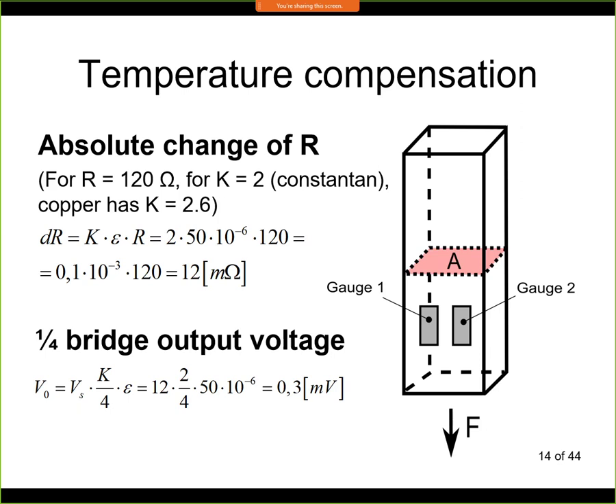What will be important will be the temperature coefficient of electrical resistance. So if I calculate the resistance change in ohms, here we have the gauge factor, we have the strain, and we have the initial resistance. I have chosen the 120 ohm strain gauge, and this will give us a value of about 12 milliohms. Again, this calculation is not entirely accurate, because for copper I would need to use 2.6, and here for Constantan 2.0 or 2.1. But anyway, we can see the range. Initially we had a 120 ohm strain gauge, and this is a change of about 12 milliohms.